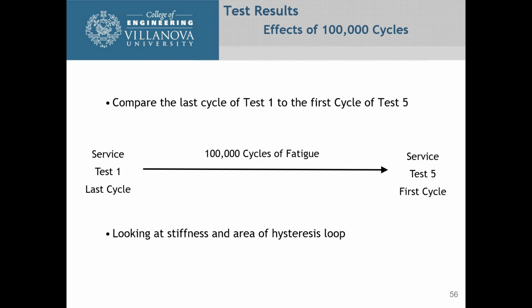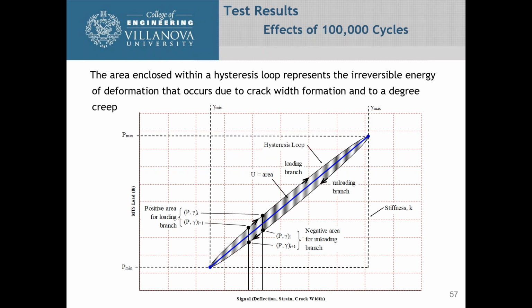So what you're going to do is compare the last cycle of test 1 to the first cycle of test 5, because within that range was test 2, 3, 4, and that's where you were loading it to 100,000 cycles with the 100,000 cycle load. So by looking at the stiffness and the area of the hysteresis loop, we can get an idea of what the effects were.